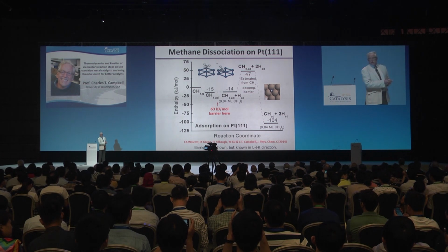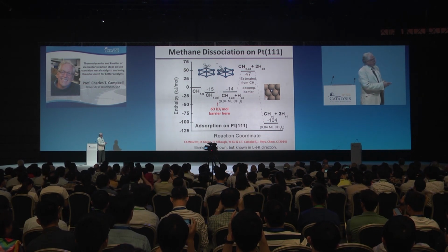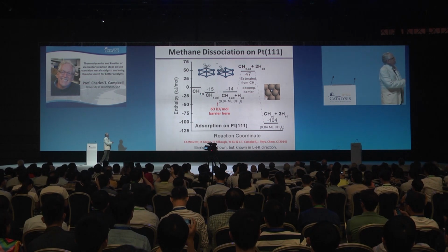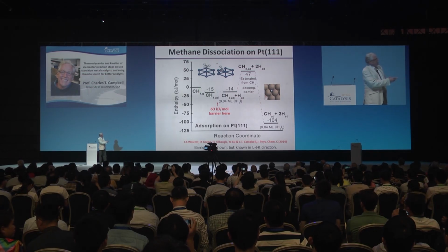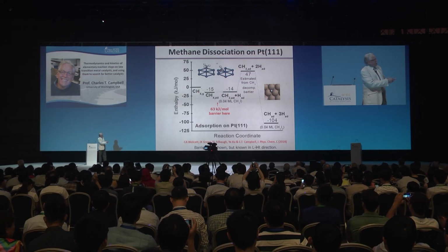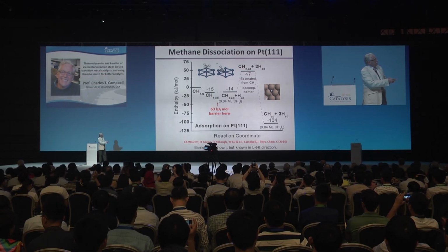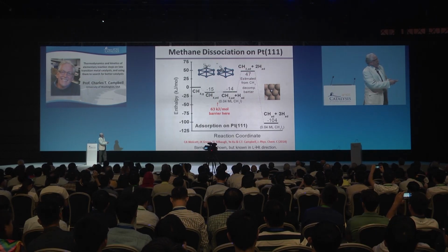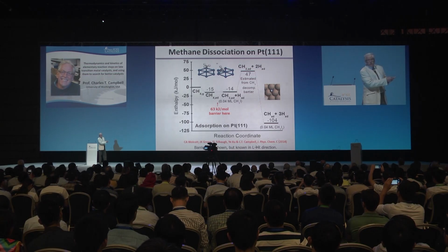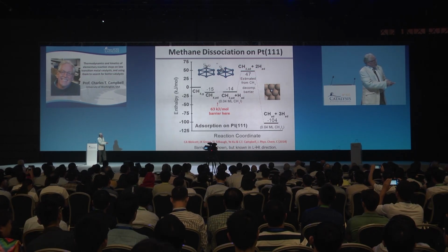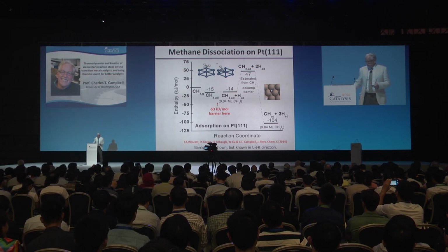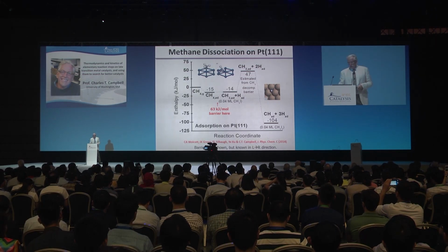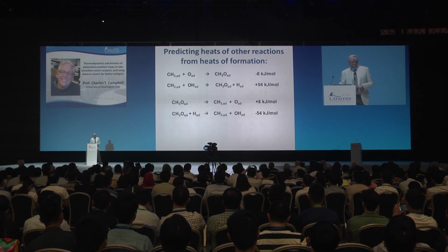So putting those together, we can start to make energy diagrams for important reactions like methane activation. So this is methane gas, weakly absorbs to make methane on the surface, loses one hydrogen, that's almost thermal neutral. It loses another hydrogen, that's way uphill, and then finally the third hydrogen, and it's way downhill again. So we can get a handle on the energetics of the overall steps.